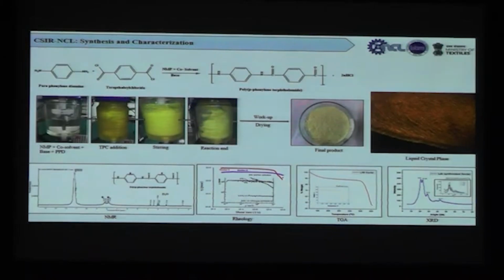But fortunately, these materials are rigid rods and they align to form what is called the lyotropic phase, which means a liquid crystalline phase. In that phase, even when you increase the concentration, once it starts aligning, the viscosity drops. So that phase can be used for spinning. What is shown here is a birefringence when you observe this polymer in sulfuric acid under the microscope. It says that the polymer that we have developed at NCL is of the right, high molecular weight, so it is aligning to form this lyotropic phase.